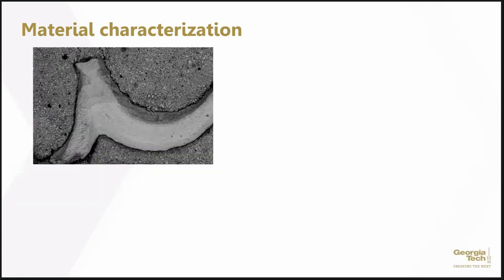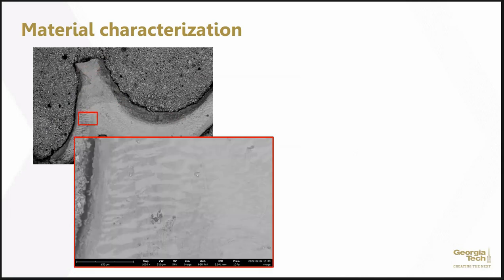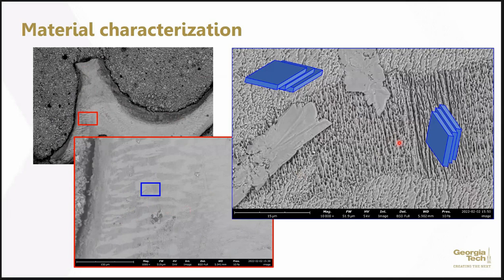Here are a few additional ones. That's the shell outer side, and that's the shell inner side. That's actually a denticle, a broken denticle. If we zoom in to look at the middle part of the shell, they have braided patterns. And if we zoom in, they all have very different structures that can make them stronger.